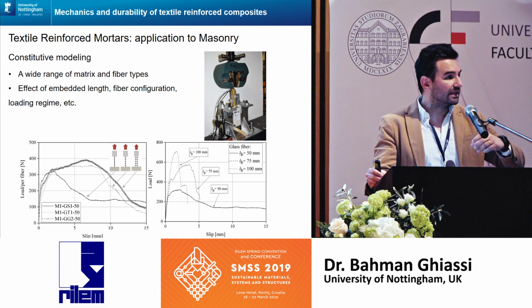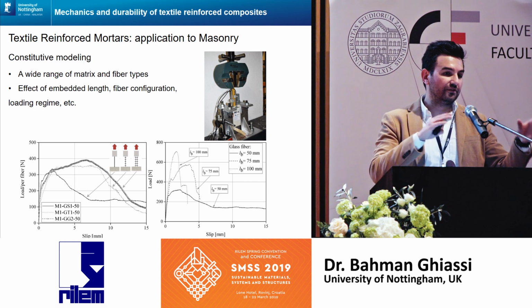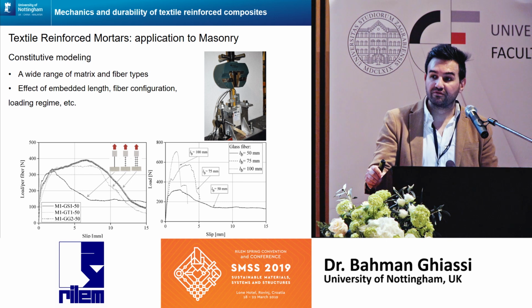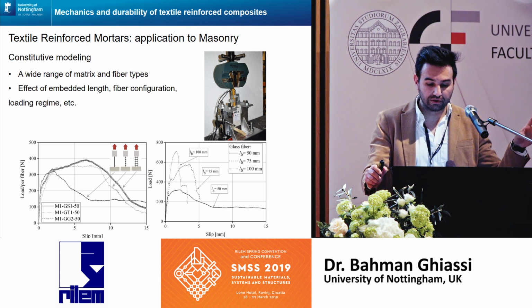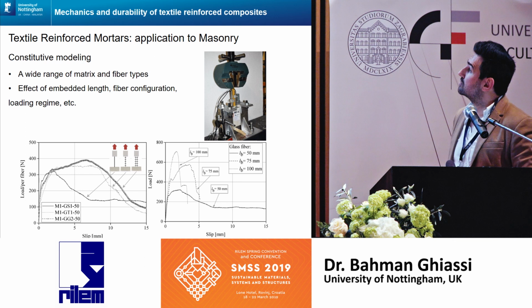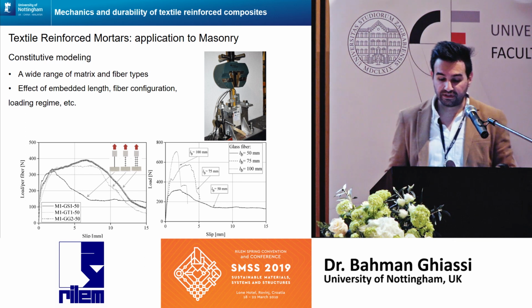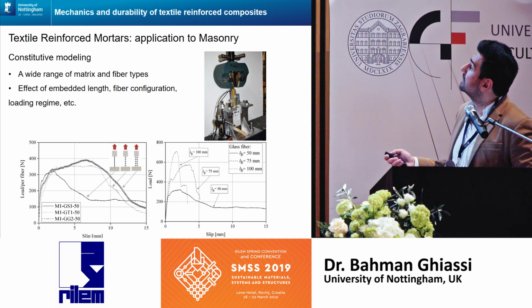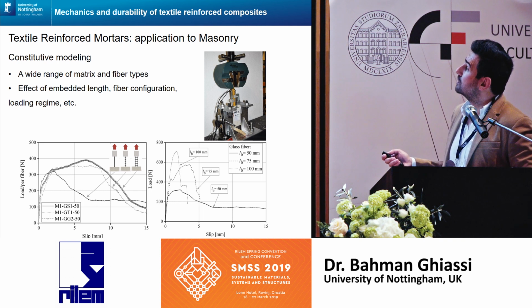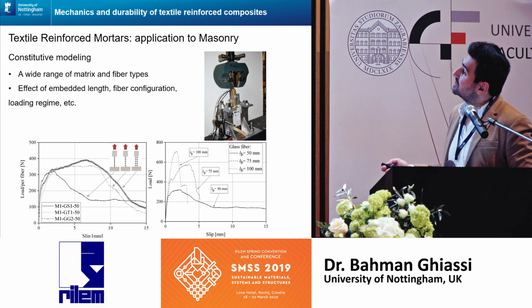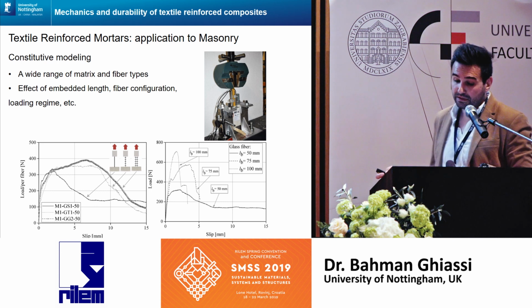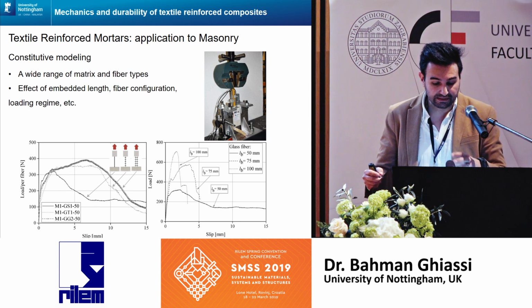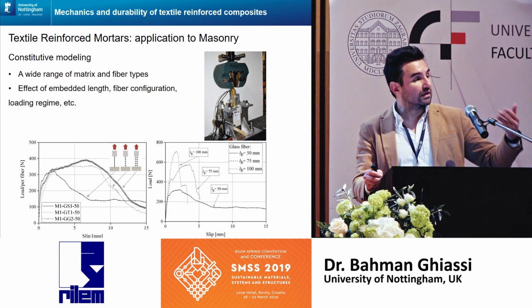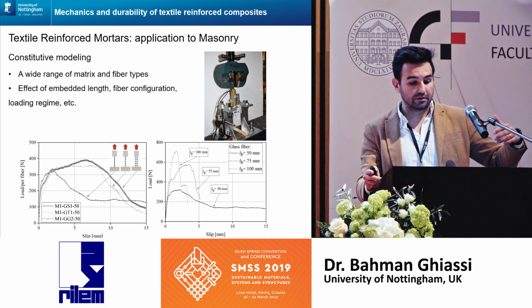So we investigated how these combinations of fiber and mortar types can affect the performance at the local level and at the structural level. For example, I'm showing here some results of pull-out tests showing how effective bond length, for example in glass fibers embedded in pozzolanic lime, can change, or how the transverse fibers in bidirectional fibers can change the pull-out response significantly. So these observations should be considered in the constitutive laws that we are developing later on, right?